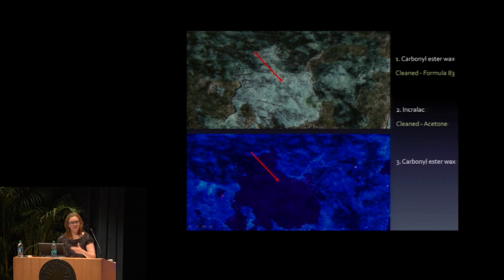So then I cleaned with acetone, thinking I'd remove the Incralac. And there seemed to be something else that showed up that was fluorescing an orangish color. And so we sampled that, and we found an ester wax. So again, that's not something that I really expected. It makes complete sense now, but often you'll have a wax coating put on at the foundry, and then somebody will put an Incralac on top of that, and then we wax on top of that for maintenance. So we have really 3 layers here, and that's really going to affect our system that we choose for cleaning.